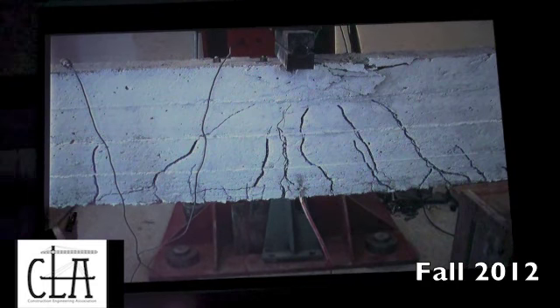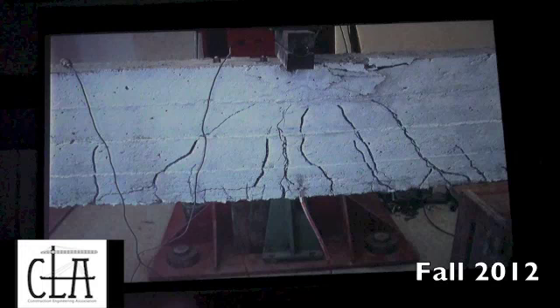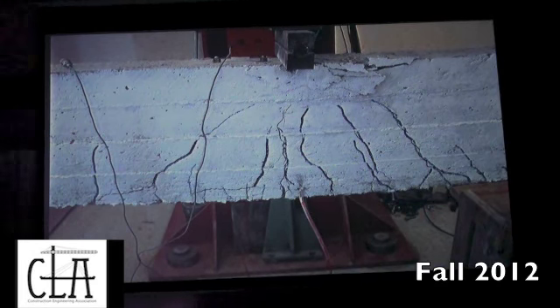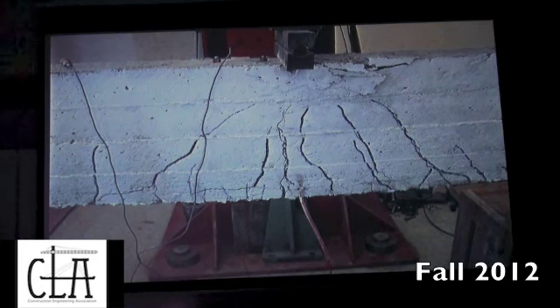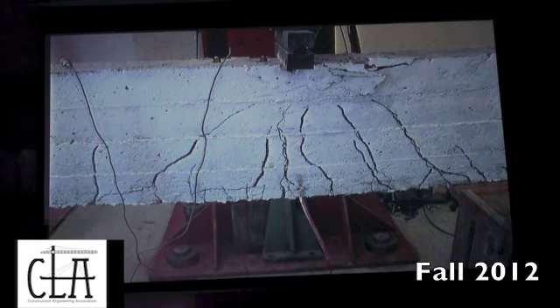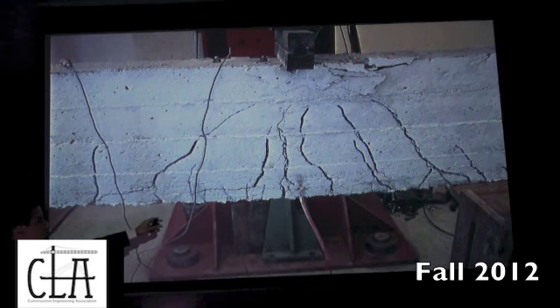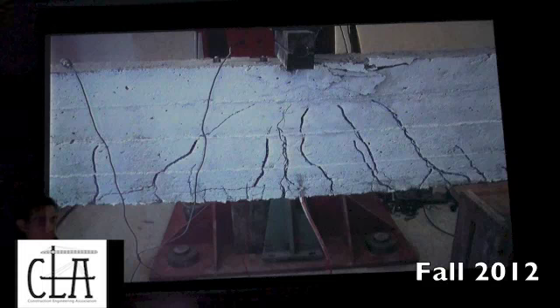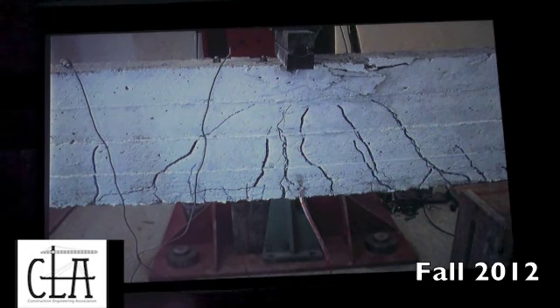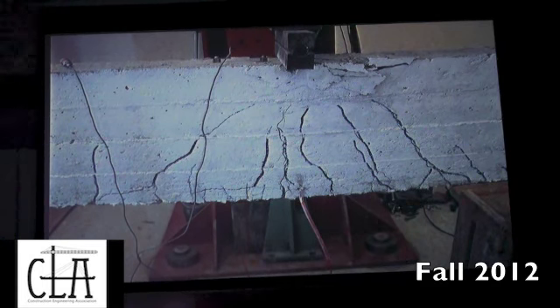As you can see, these are the cracks on the control beam, and they are concentrated in the middle span, which corresponds to our design, which is flexure failure. Later on, we're going to attach the CFRP laminates. The cracks are going to move down and horizontally until they reach the epoxy layer, and then the bonding failure happens.